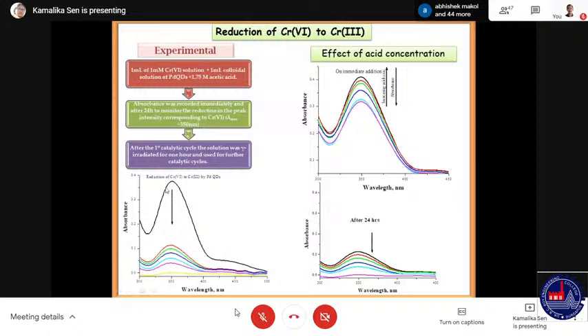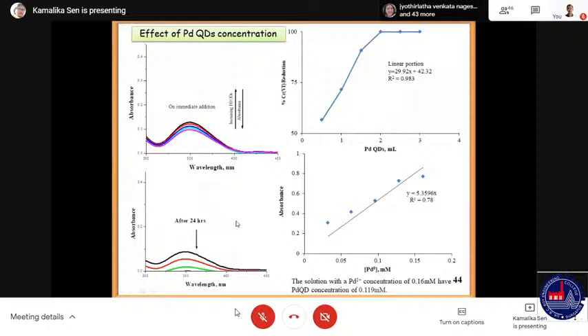acetic acid is used, and here we have seen that with increasing concentration of acetic acid, absorbance decreases, and with time also absorbance decreases. That is, high acetic acid concentration increases the efficiency of chromium 6 to chromium 3 reduction, and same as with time. And this is the reduction of chromium 6 to chromium 3. With increasing palladium quantum dot, there is not much decrease in chromium 6 to chromium 3.